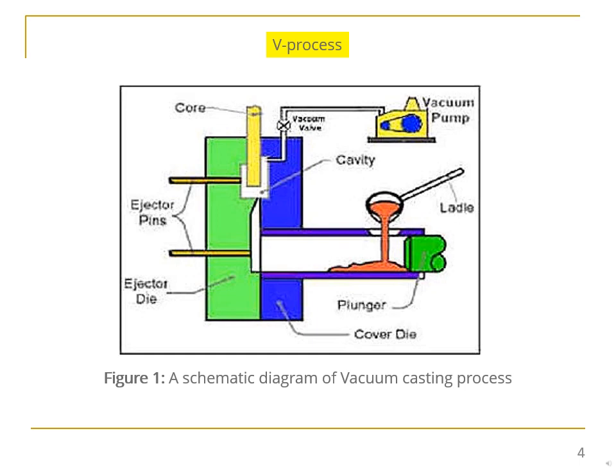This significant reduction in the volume of gas porosity and the pore sizes in castings has the result of markedly improving the density and tensile strength of the end product. A good vacuum in the mold cavity enables the alloy to flow into blind recesses in complex shapes. It also allows the fronts of the molten metal to merge freely without forming cold shut failure.